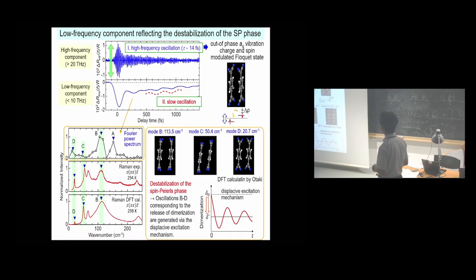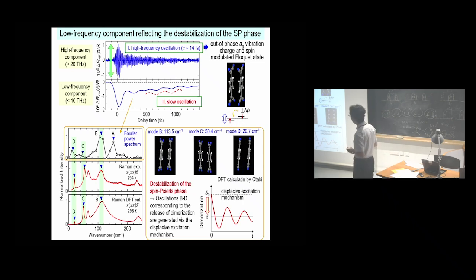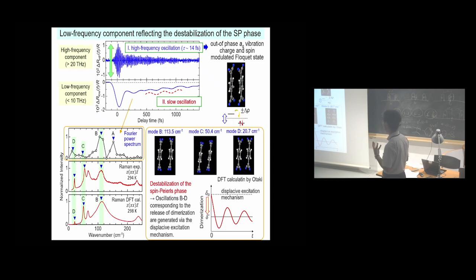Next, I will discuss the low frequency component reflecting the destabilization of the spin-Peierls phase. Its Fourier power spectrum is shown here. 4 oscillations are observed like this, and by comparing these oscillations with the Raman spectrum, these 3 oscillations, B, C, and D, can be related to these 3 Raman modes, which are illustrated here. All these Raman modes modulate the dimerization. This result suggests that the out-of-phase Ag mode vibration, this high frequency oscillation, destabilizes the spin-Peierls phase, and